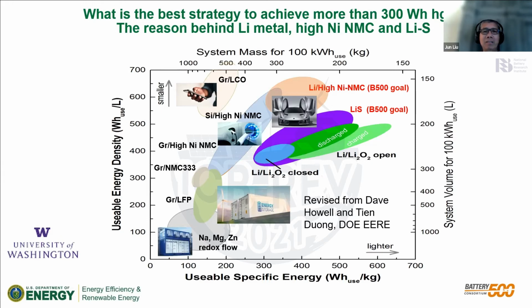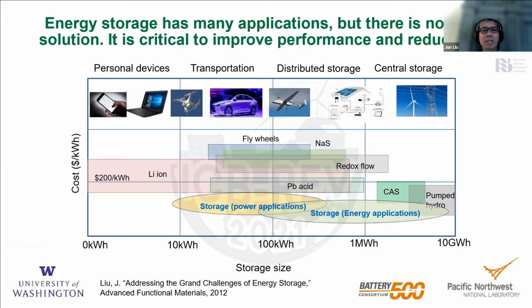One, lithium metal anode with high nickel NMC. Two, lithium sulfur, lithium anode with sulfur. Both of these have potential to get to close to 500 watt-hour per kg. And the difference between the two is the NMC system has a higher volumetric energy density, and the lithium sulfur system may have a higher gravimetric energy density, but both of them are very interesting to study.